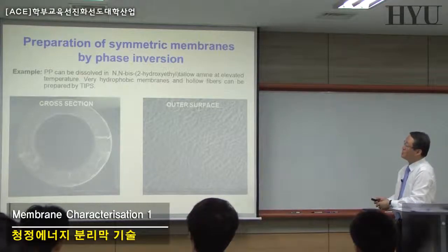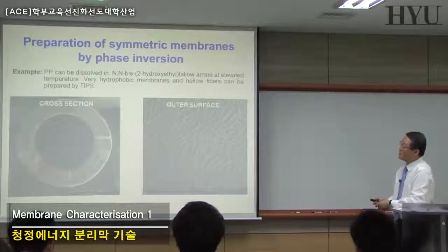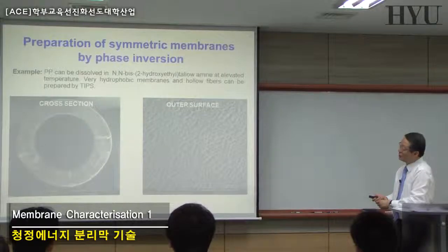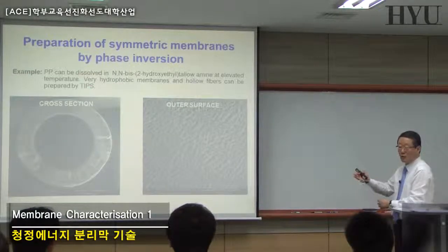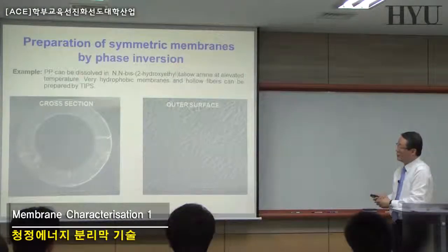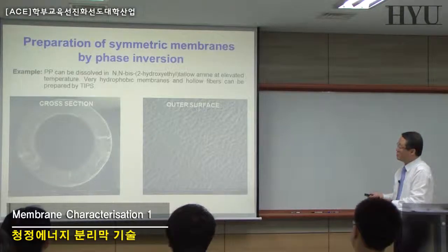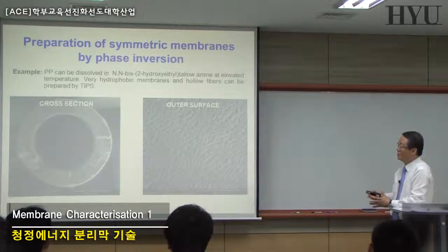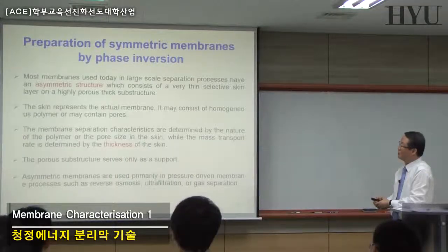We can make the symmetric membrane with the TIPS process, and this is an example of a polypropylene hollow fiber with a similar structure from the top to the bottom, or from the surface to the bore or inside. Using the TIPS process, we will talk in more detail about what TIPS is, but you can make a symmetric structure in this case as well. The outer surface looks a little rough, but it may have a very small pore. But anyway, you can make a very symmetric structure.